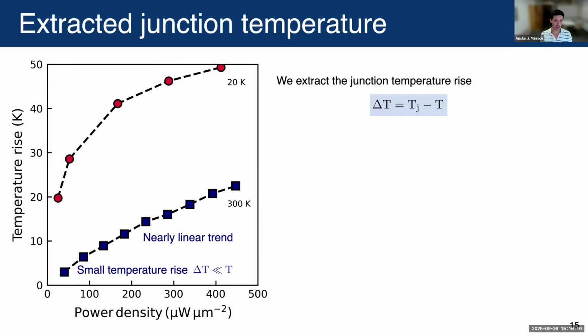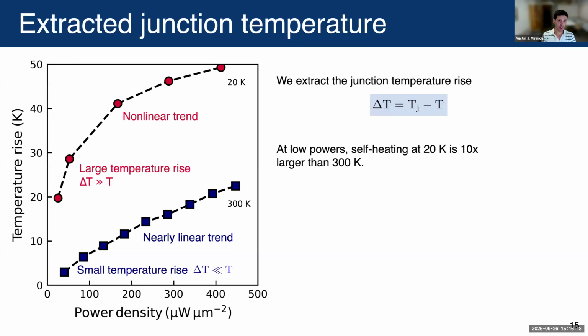Now at 20 Kelvin, the story is completely different. You can see it's not a straight line anymore. There's this curve. And the temperature rise is even a few times that of the base temperature. You can see the maximum temperature rise is 50 Kelvin over a base temperature of 20 Kelvin.